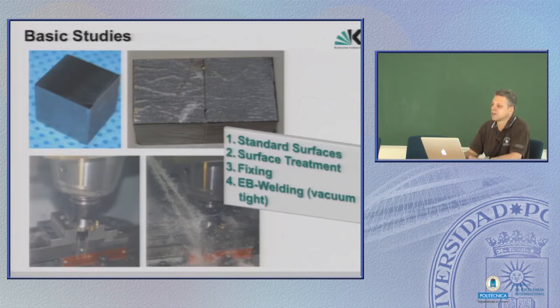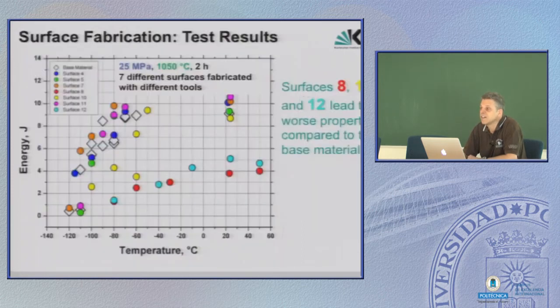We have tried to establish step by step how Eurofer behaves, what you can do, how it performs under welding. So we first started with the examination of fabricating different surfaces for diffusion welding. We used these tiny walls of Eurofer, then by several milling tools under several milling conditions and parameters, produced many kinds of different surfaces, fixed them together, welded them tight, put them in a hot isostatic press, and examined them. For the examination, especially quick examination, we used Charpy specimens and Charpy tests with the notch exactly aligned on the weld line. This is the best mechanical test you can do, because welds are rather sensitive to breaking, so Charpy tests are perfectly well suited for that.